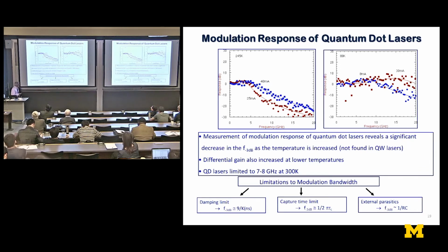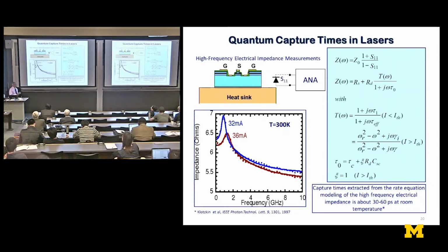Now, the modulation bandwidth of a laser is limited usually by damping. But it could be limited by capture time, and I thought, well, if it is limited by capture time, then we can do an experiment that electrical engineers do. And that is to measure the high-frequency impedance of a diode. And we measured that, and we analyzed the impedance data, as you see, with the rate equations. And out of all this comes out this quantum capture time.